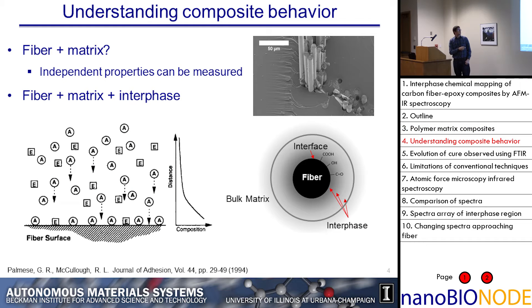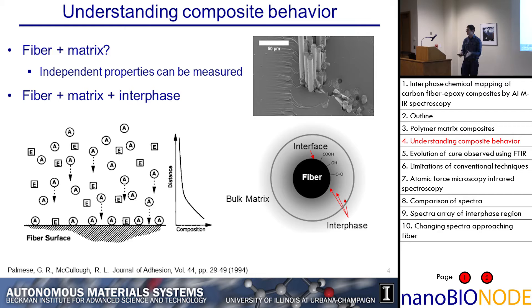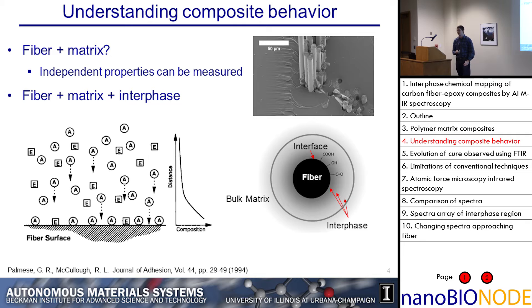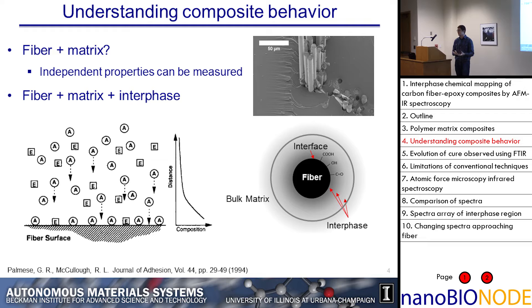We really want to understand the behavior of these materials. The question is: is it okay to look at the fiber and the matrix as independent constituents, measure those properties independently, and then come up with models that describe the material that way? What I'd like to point out is that composite materials aren't just a mixture of the two components — a very important aspect is the interaction between those two components. Depending on the interface, you can have fibers pulling out of the matrix, or if a crack propagates it might crack directly through the fiber depending on the fiber-matrix interaction.